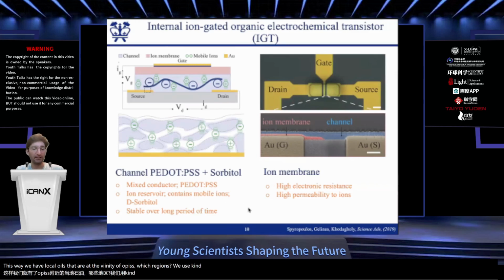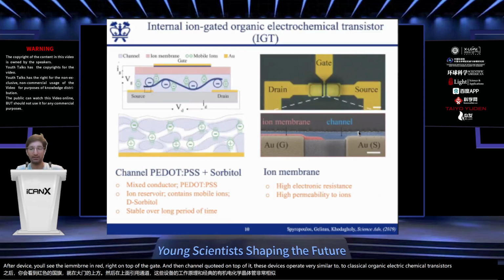We use chitosan, an abundant polysaccharide, as our ion membrane because it has very good ion conduction. It's processable, but also an electronic barrier to form the junction between the gate electrode and our channel. So this is how the cross-section of the device looks. And if you take an SEM image of the device, you'll see the ion membrane in red right on top of the gate, and then the channel coated on top of it. These devices operate very similarly to classical organic electrochemical transistors, with very high transconductances.